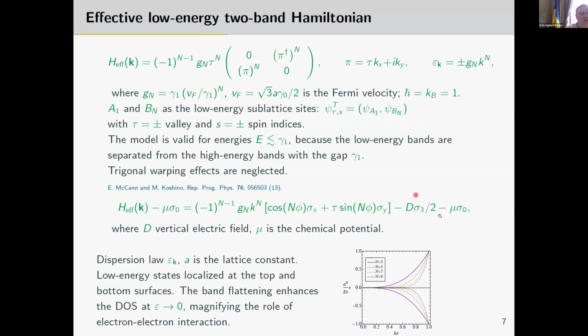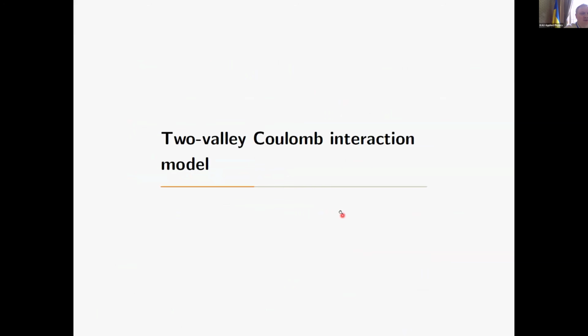If we also add a term, in this language, the vertical electric field, the spectrum is plus or minus k to the power n, but the vertical electric field also opens an additional gap in the spectrum. So this is a controllable parameter, and another controllable parameter is the chemical potential. And this is a picture of the band dispersion and why it's interesting for flat bands.